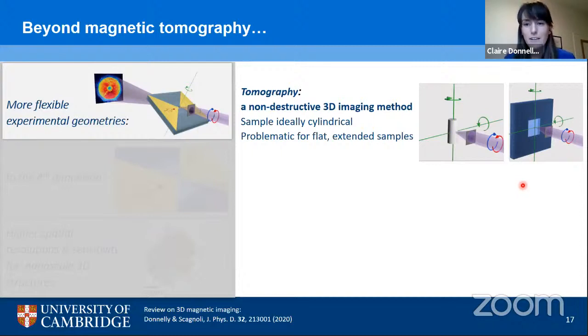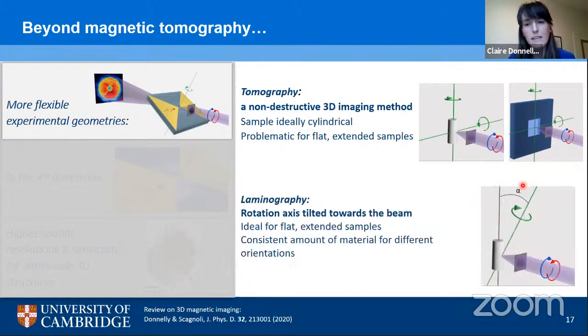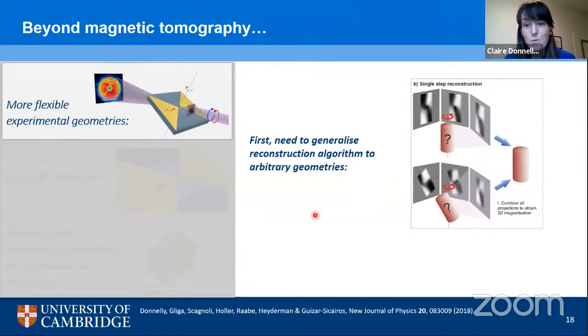Now, a technique or a geometry that actually gets around this challenge is laminography. With laminography, as opposed to tomography, our rotation axis is actually not perpendicular to the X-rays, but it's tilted towards them, meaning that for flat extended samples, we don't block the beam at any particular angle. So before we could go on to an experimental demonstration of the laminography, we first needed to upgrade our reconstruction algorithm, which previously had assumed a tomographic geometry.